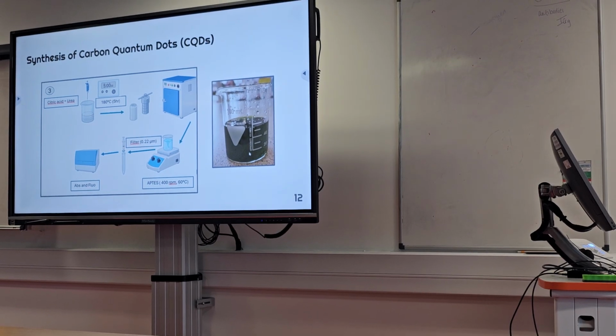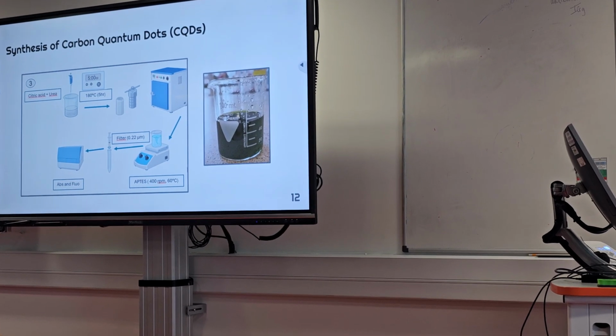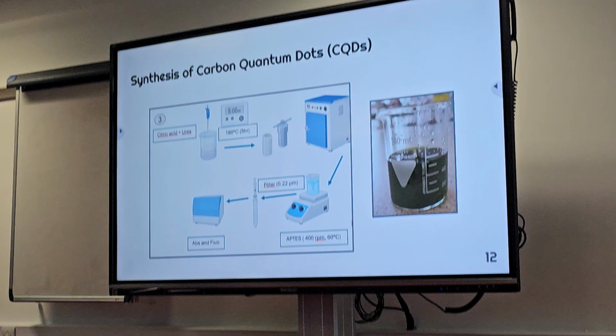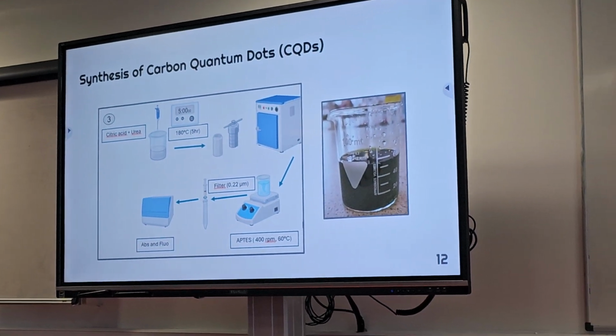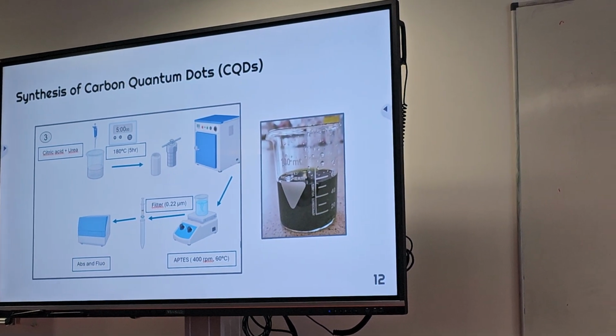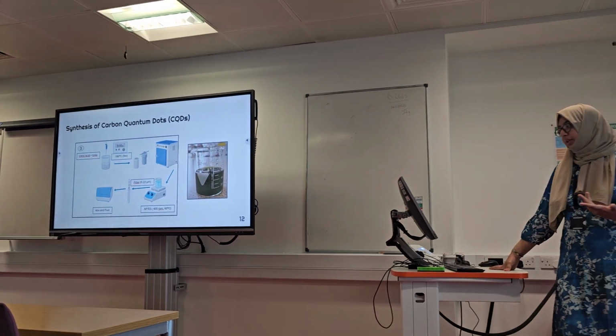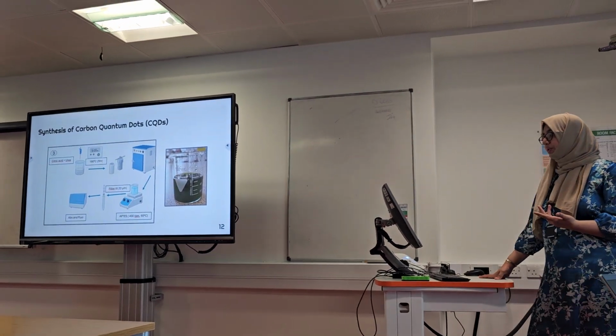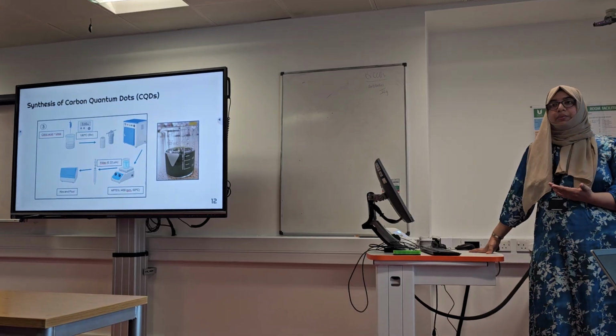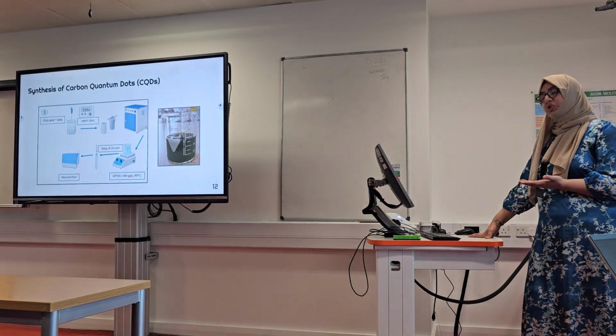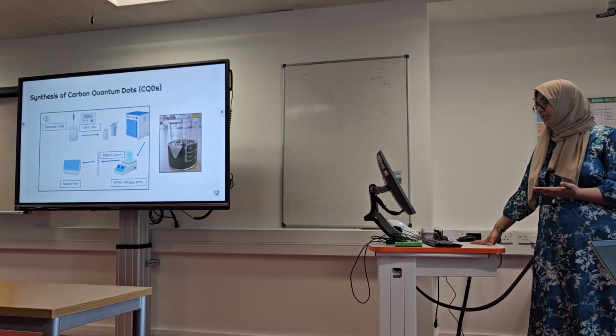Okay, the third method I use citric acid and urea. The first was with APTES, the second I used citric acid and EDA. The third one I use urea for the nitrogen doping. So I put it into the hydrothermal reactor for 5 hours at a temperature of 180 degrees centigrade. The rest of the procedure is the same.